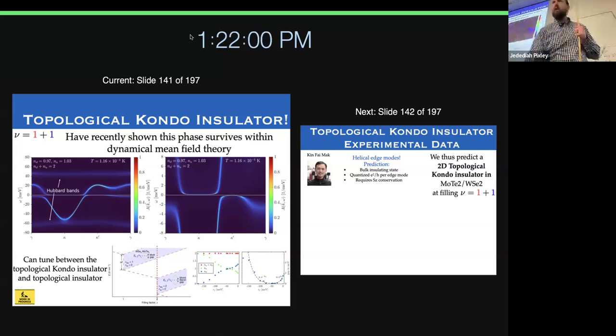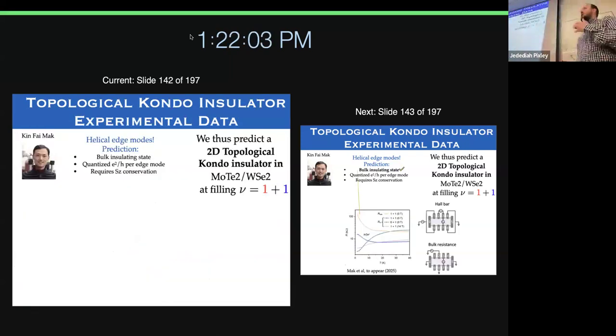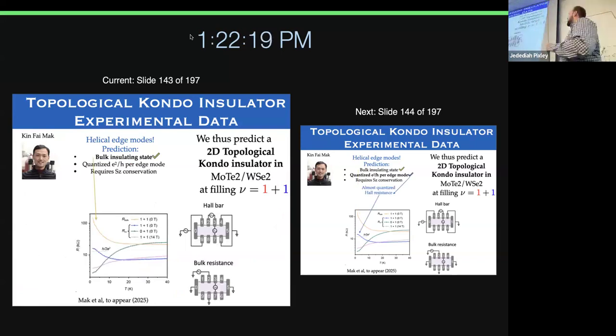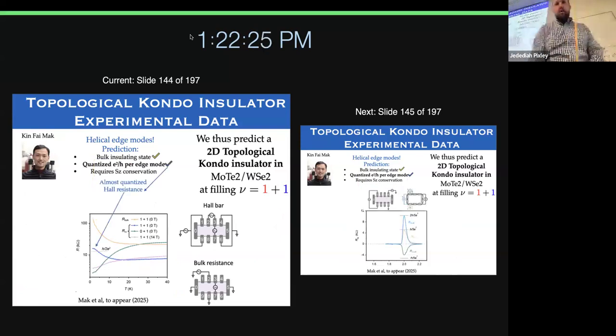So yeah, Kin Fai Mak from Cornell was very gracious, and he gave a seminar a couple weeks ago at Rutgers, and then he shared this data with me. Okay, so we made this prediction. This is a prediction, not a post-diction, okay? So one plus one, there should be a topological Kondo insulator, MoTe2 WSe2. So here's the data. So they have a bulk insulator, the clear bulk insulator. They try to see the edge transport. So now this is the quantized conductance, Hall conductance, almost 2 e squared over h, almost.